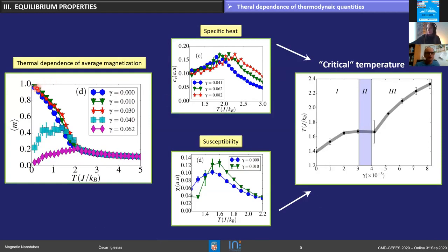The first thing that we can study is how the magnetization varies, for a given nanotube radius and length without varying them, as we vary the competition between dipolar and exchange interactions. As you keep increasing dipole interactions, the magnetization of the tube varies, and you see that when exchange dominates, it orders ferromagnetically, and when dipolar interaction dominates, magnetization becomes zero, and in the middle you see intermediate states with some intermediate magnetization.